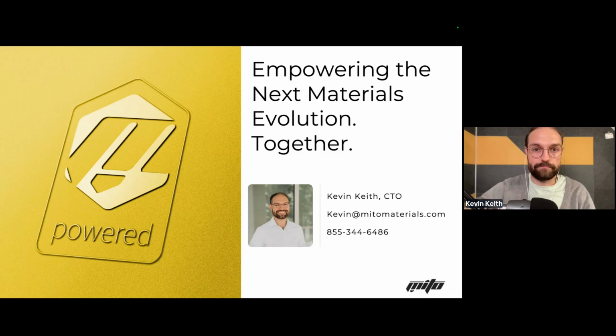Okay. What is the upper limit for how much you can include in an application, and what happens if you have too much? Graphene is one of those weird materials that less is more. For instance, if you include too much, you start getting a decrease in mechanical properties. And when I say too much, I'm talking 1 to 2%. At that point, you start getting bigger decreases, specifically in epoxy carbon fiber systems. Most systems degrade 5 to 25% at that 1% loading. I typically don't like going above that because at that point it becomes not only cost prohibitive, but you start